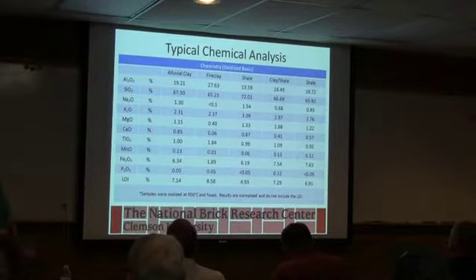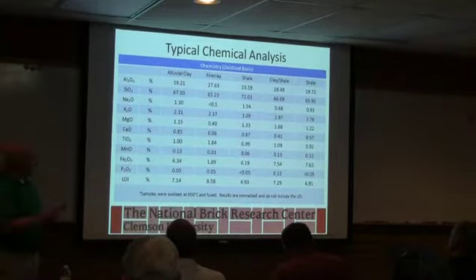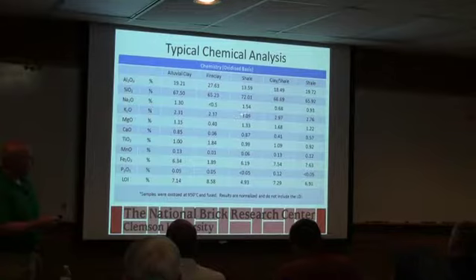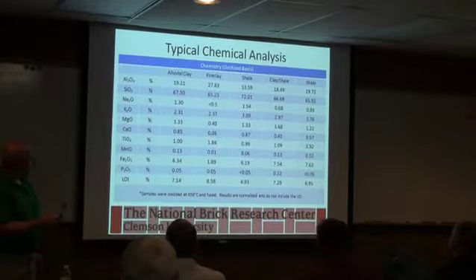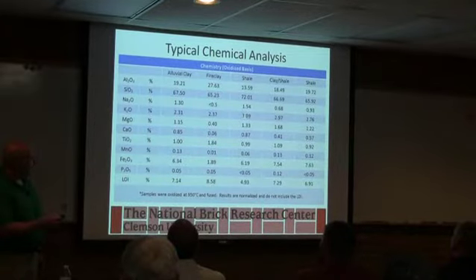So as a rule of thumb, I assume everything's 2,000. And depending on how high this number is, I go up or down. Okay, it's not perfect. It's just kind of an art thing that I've picked up over time. But I would expect this material to have the lowest firing temperature of the group because it's got the highest sodium and potassium number. So those are real good indications of what's going to happen in the kiln when you fire the material.